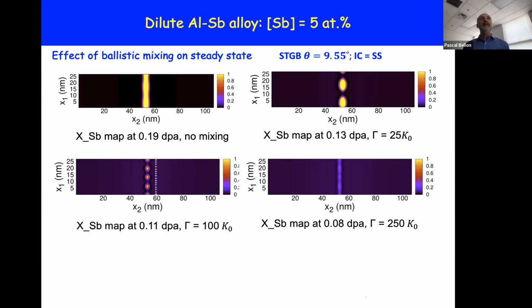Yes, right. This is a very good question. We know that in irradiated alloys or microstructures, low angle and special grain boundaries behave very differently. For instance, coherent twin boundaries, sigma 3 twin boundaries, are poor sinks, so they will not collect many point defects, and segregation would be essentially very limited there. Whereas large angle grain boundaries are good sinks, they will collect a lot of solute in a system where radiation-induced segregation takes place, and so we expect the behaviors to be different.